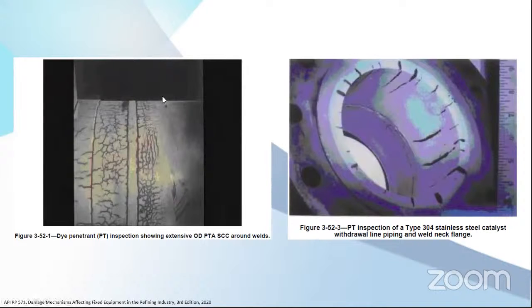So it always happens around welds because of the stress. It's branching cracks, and only happens where the equipment is operated at sensitization temperature with sulfur compound. If you don't have the sulfur compound, then you will not have this polythionic acid stress corrosion cracking.